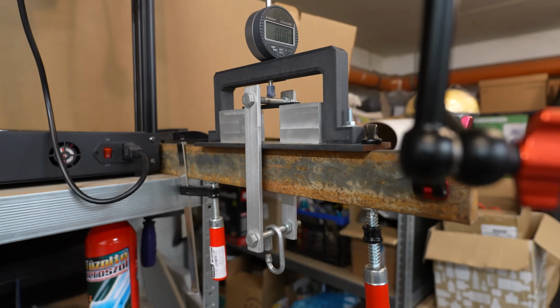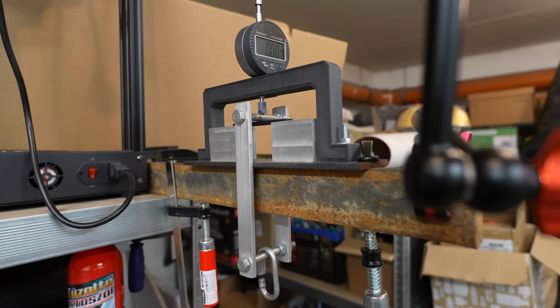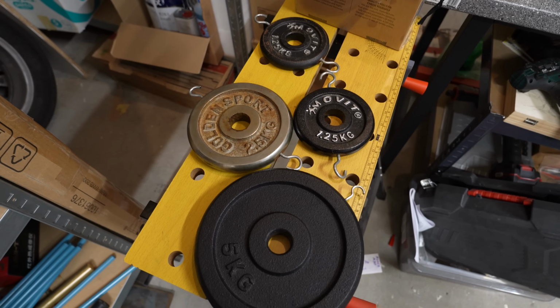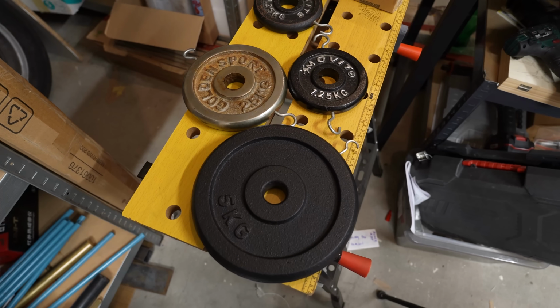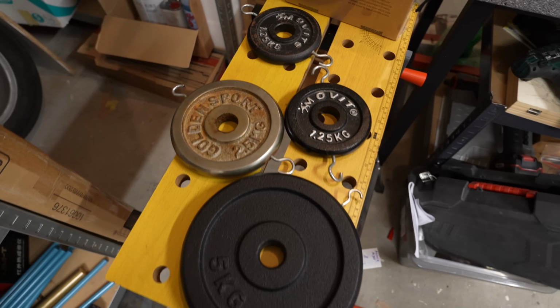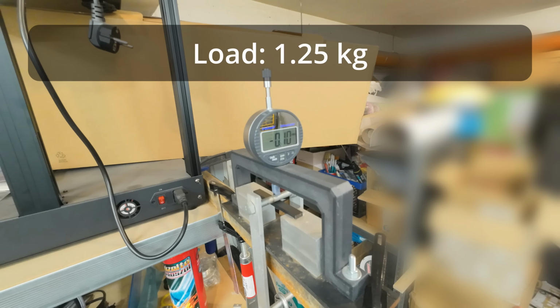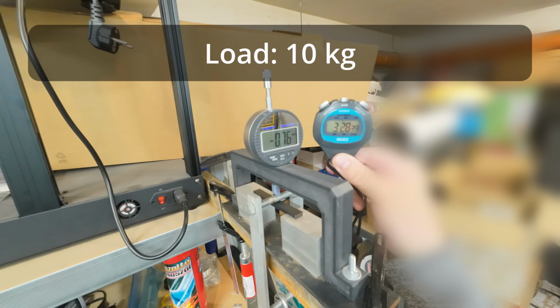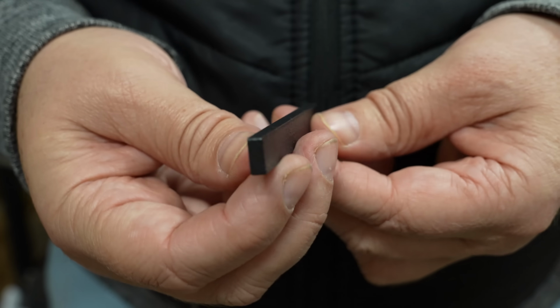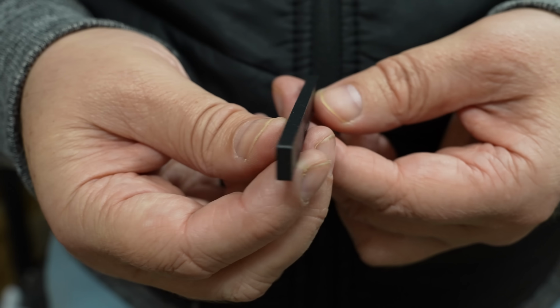3-point bending test. Distance between supports is 50 mm, and these loads will be placed one by one, and I measure the deformation after 30 and 60 seconds. Having only one object in this test may be boring, but pay attention to that additional deformation during this 1 minute. Now the load is 5 kilograms, and not even the load of 10 kilograms will make additional deformation during this 1 minute. This load was nothing for this PPS-CF.